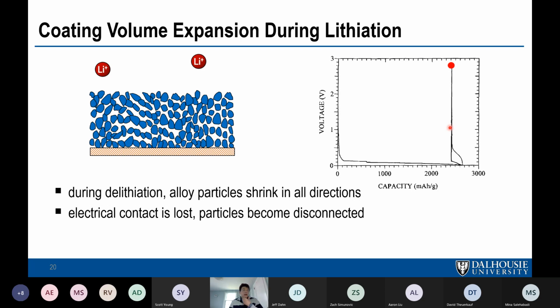So before we could have learned about the electrochemistry of silicon, we had to solve this problem. And a lot of the work early on, the solution was just to put a lot of carbon black and a lot of binder into the coating with a little silicon. And you could get silicon to cycle decently enough to figure out its electrochemistry. And that's basically what the early papers did.